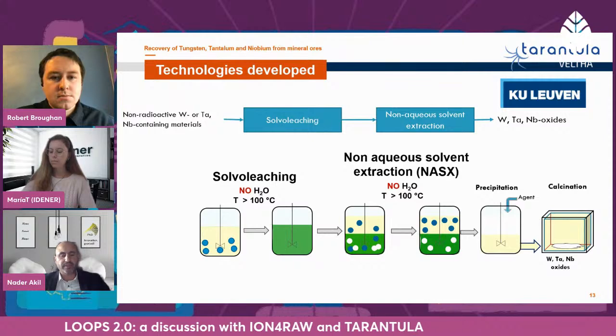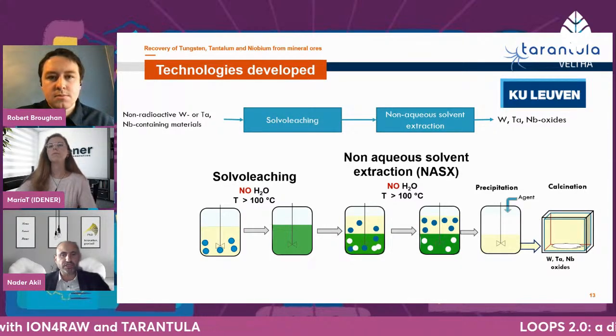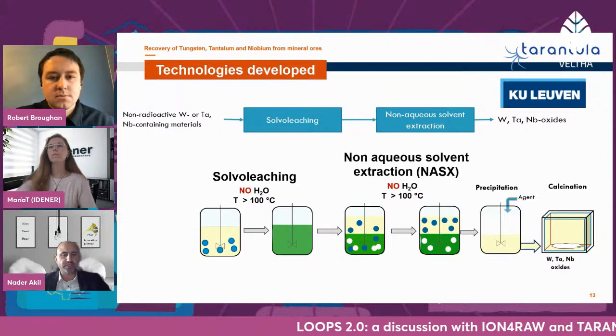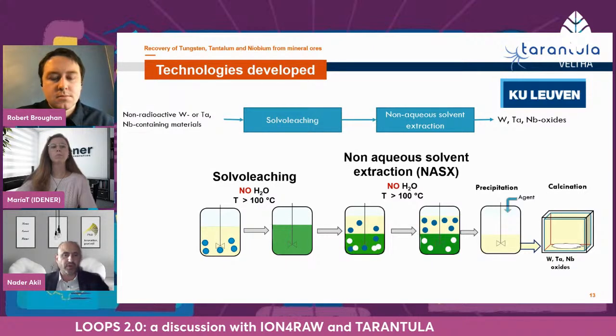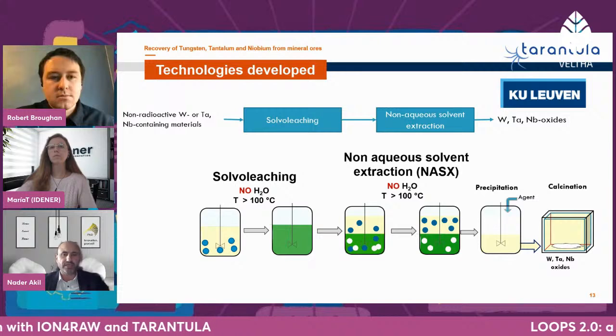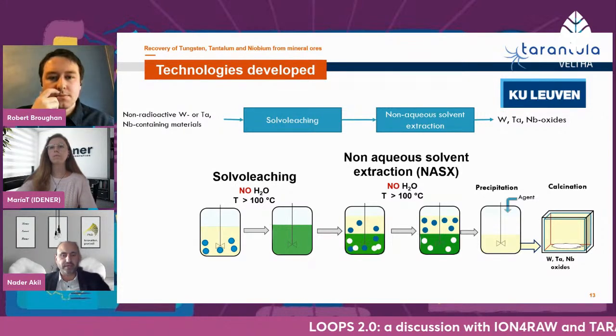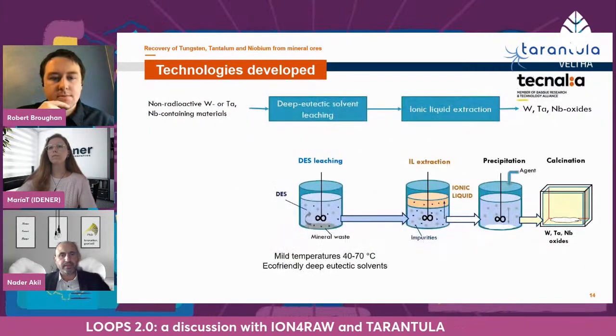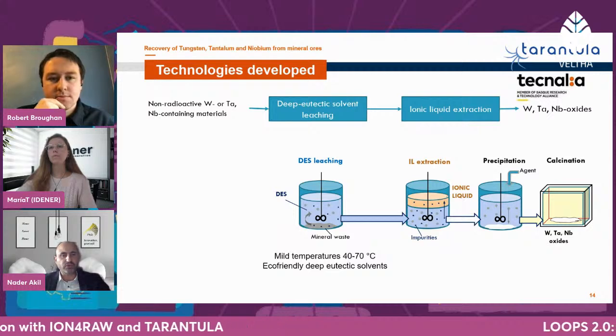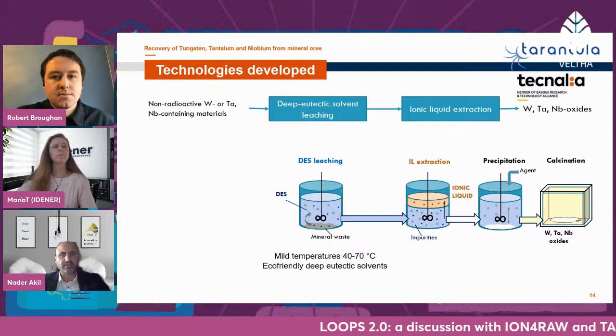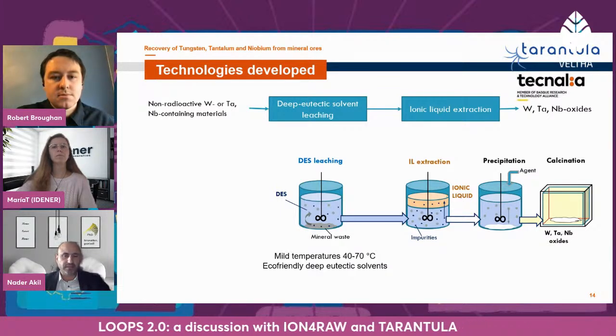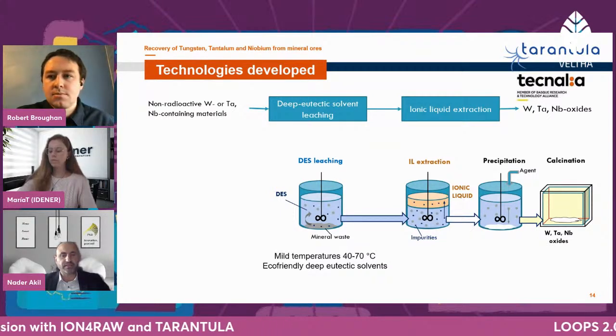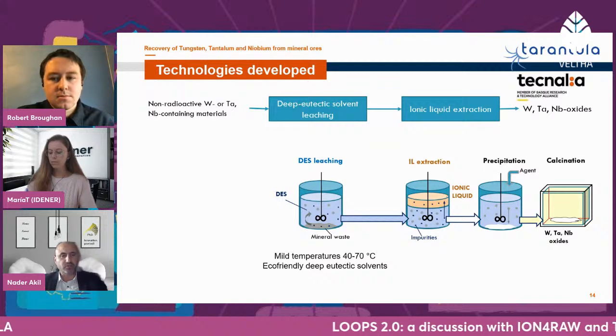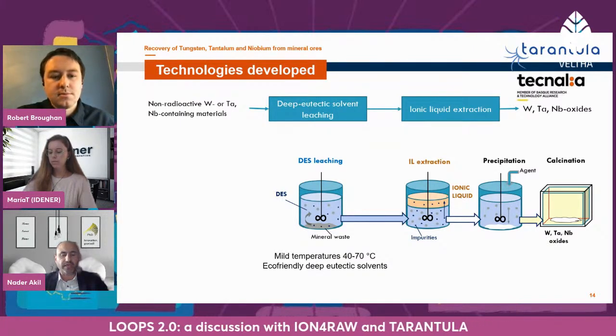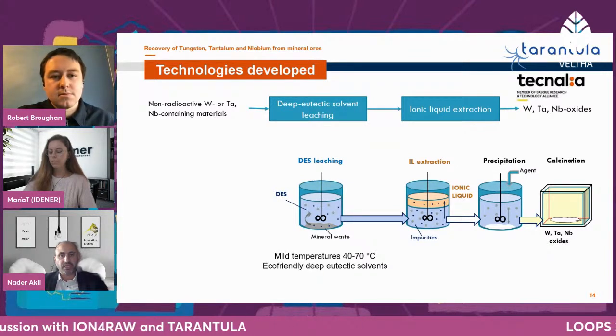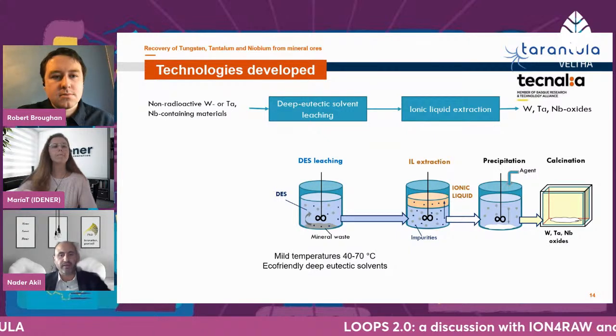With the KU Leuven process, we are using solvo-leaching and non-aqueous solvent extraction. This is a process which is known to reduce quite a lot the consumption of water. When it is followed by precipitation and calcination, we can obtain the metal oxides. The process of Tecnalia focuses on the use of deep eutectic solvent leaching and ionic liquid extraction. The importance of this process is that it is eco-friendly because the deep eutectic solvent is biodegradable, and it can work at mild temperatures between 40 and 70 degrees. Also, when followed by precipitation and calcination, we can obtain the metal oxides.